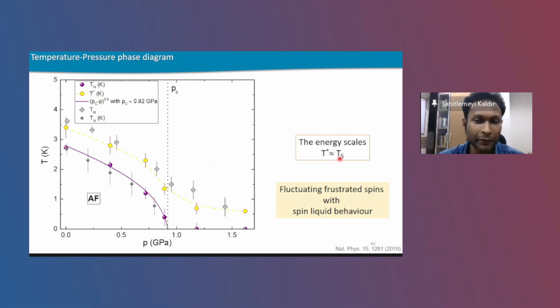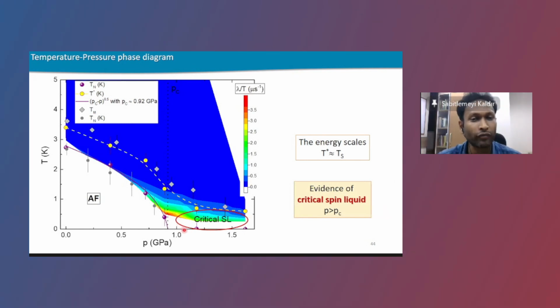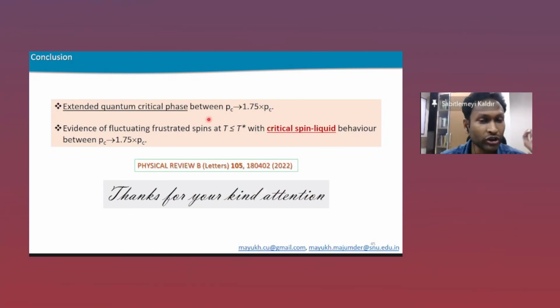And as I said, below the T star, TS temperature scale, we have spin liquid-like correlations. So we have, of course, evidence of an extended critical phase, and not only that, but also the correlation between the spins is, to some extent, similar to that of a spin liquid. In my conclusion, I would like to say that we have got microscopic, local evidence of this extended quantum critical phase in pressurized cerium, palladium, aluminum. Not only that, below a characteristic energy scale, we have seen what is nothing but a critical spin liquid. Thanks for your kind attention, and I am open to any questions and comments.